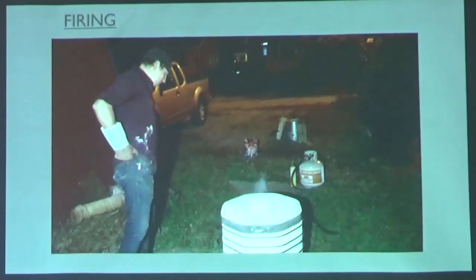But the temperature inside the kiln might not necessarily reflect the temperature of the piece inside. Obviously the piece went in at a lot cooler temperature than the kiln is. That's why you let it come up to heat, you let it soak there for a little bit, let everything soak together, get nice and even heat. Are there any more questions on this?